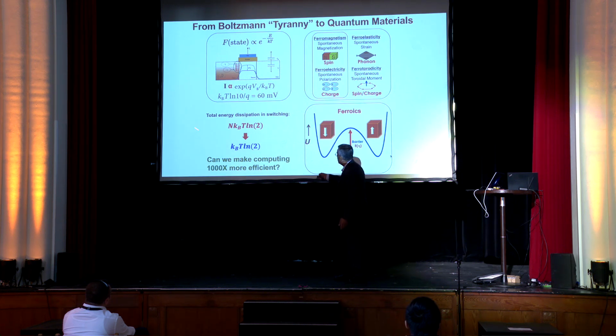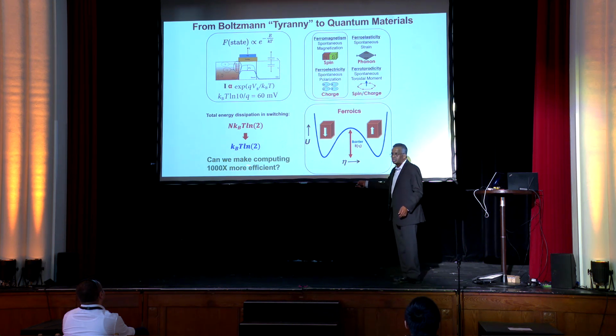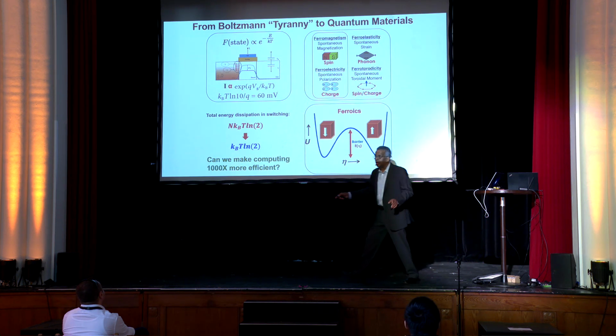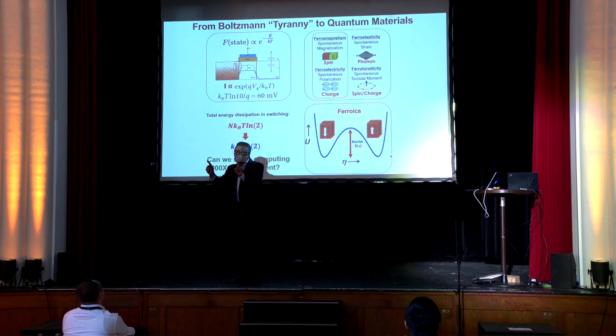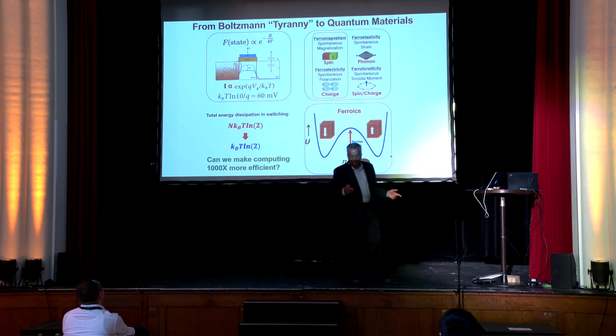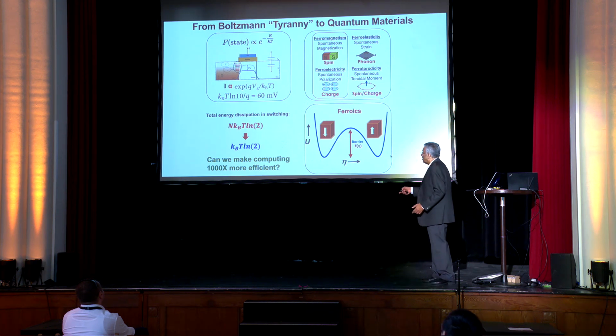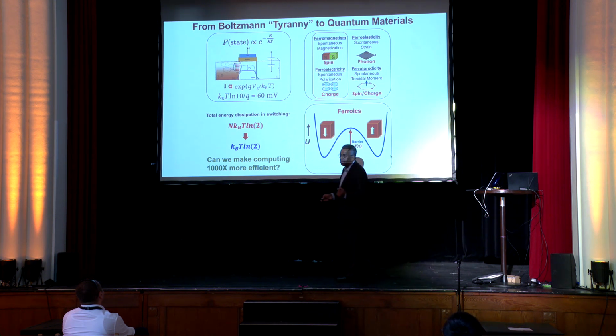So in doing so, you will go from a total dissipation in a single switching event of nkT log 2, which is simply the change in the entropy of the system as you apply the electric field and switch it. Okay? It goes from nkT log 2 to simply kT log 2. That n goes away because if you have n particles, they're all internally correlated by exchange interactions or dipolar interactions and so on. Okay? So in doing so, the question that we were asking is,